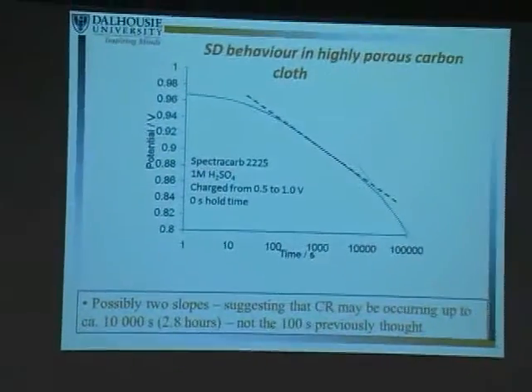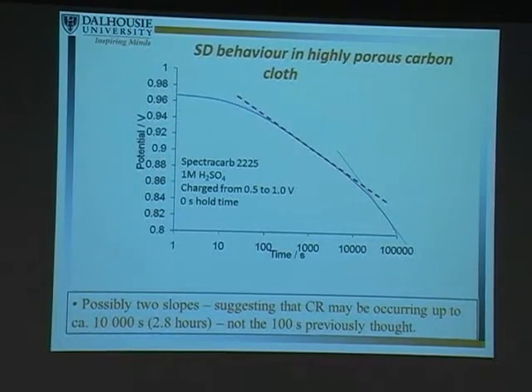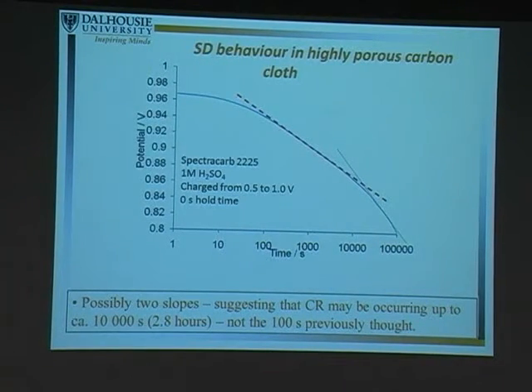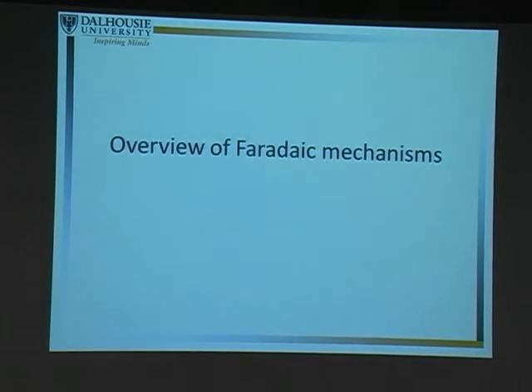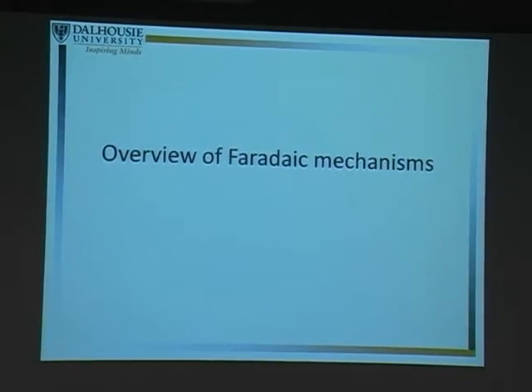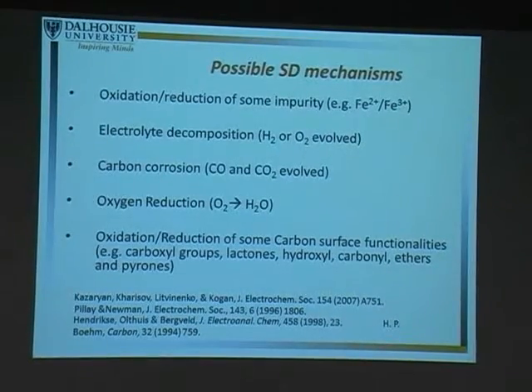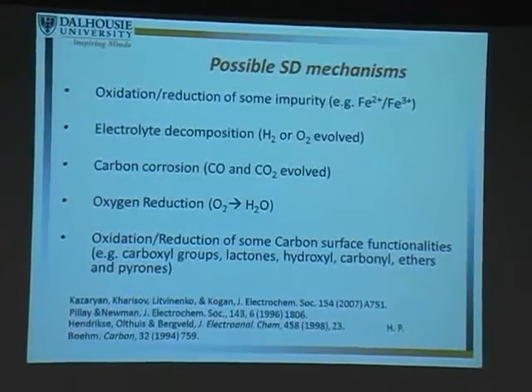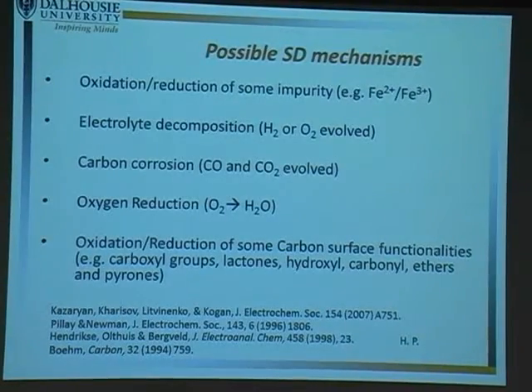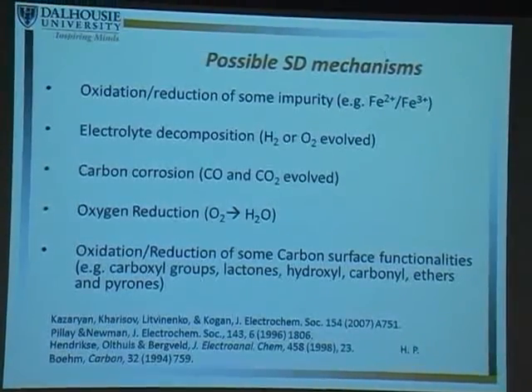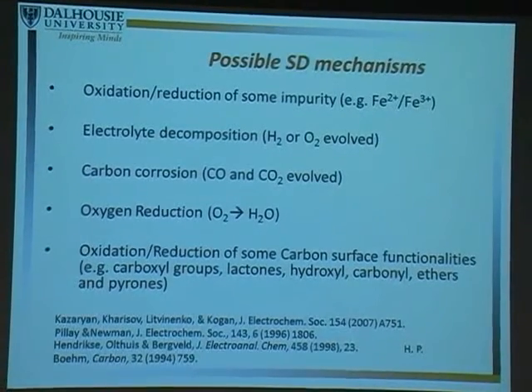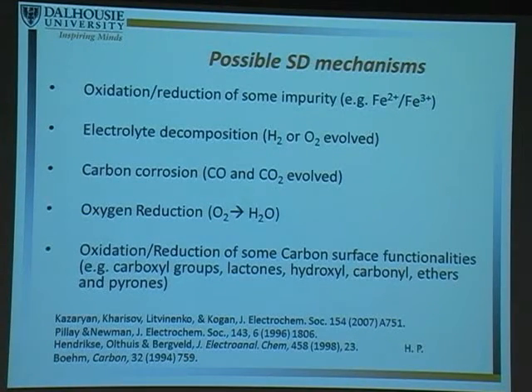Because I just showed that we believe there is a charge redistribution, but also a Faradaic reaction happening at the same time. And again, what we want to do is figure out what that Faradaic reaction is, and then how do we stop it? Because if we can stop it, we can make these supercapacitors last longer. So what we were working on simultaneously is trying to figure out the possible mechanisms. Another student and I sat down and came up with five possible self-discharge mechanisms, five possible chemical reactions that could be happening in the cell discharging the electrode.